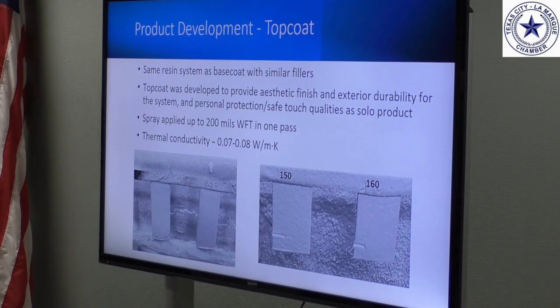So the top coat is similar. It's based on the same resin technology. The top coat was developed to give you a better, smoother surface after you apply the base coat. And the reason for that is that our industry partners would prefer to have a smooth surface compared to a somewhat rougher surface. If you are familiar with the ICRI standards, the top coat is probably a 2. Base coat is around 4, 5. So hence the need for a top coat.